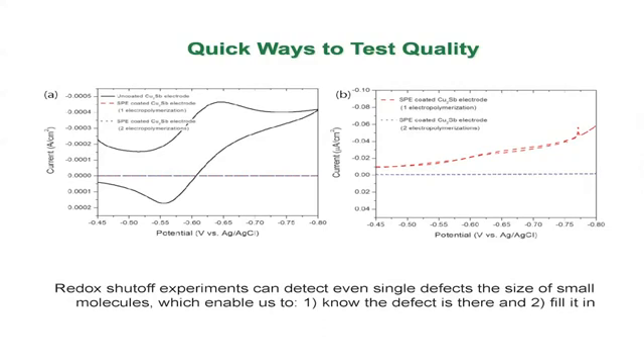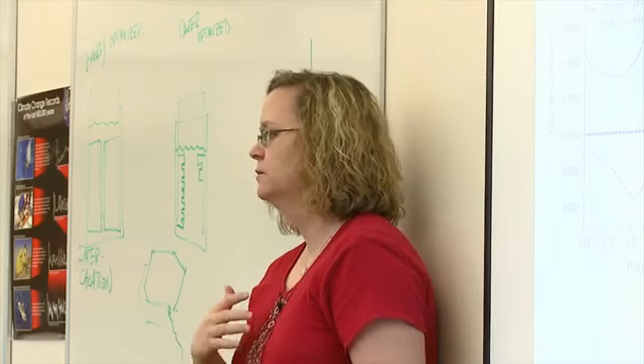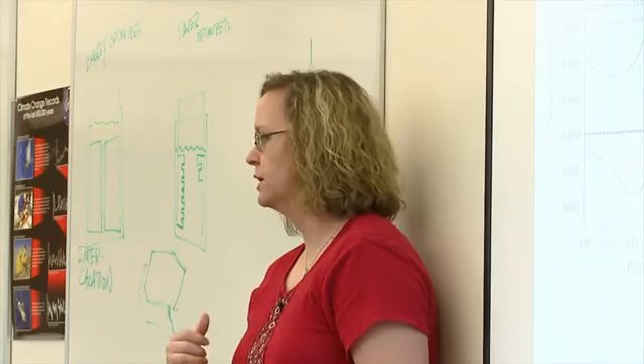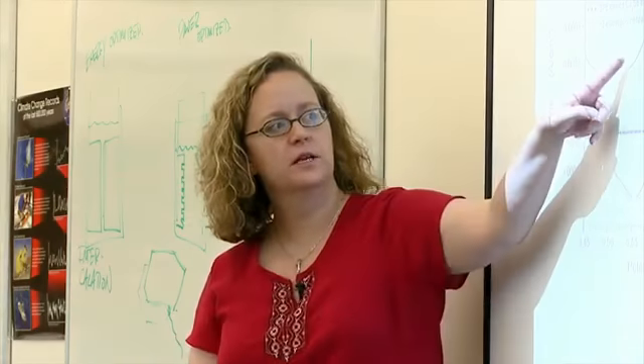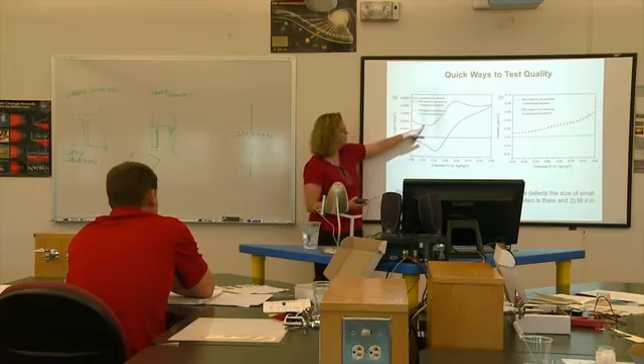So if there's a pinhole defect anywhere and we put this molecule in solution, that molecule should be able to get through that hole and we will see that duck shape. If there is no mistake, we shouldn't see anything. So we call this redox shutoff. This is what it looks like on bare copper antimonide.